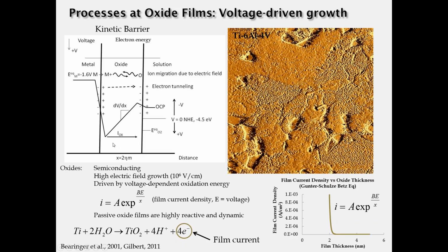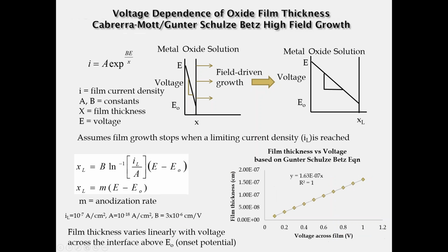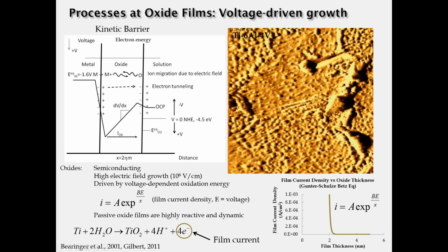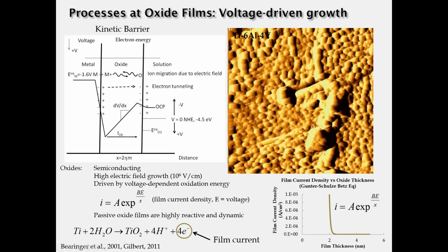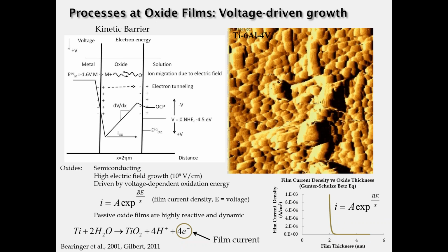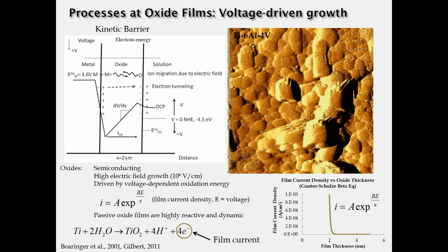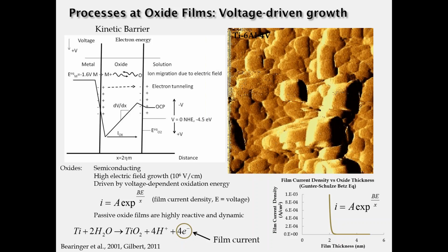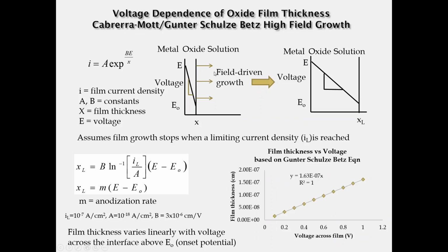And so basically, when these oxides are disrupted, they regrow to a specific thickness that depends on the nature of this equation. Let me just show you, for instance, here is an atomic force microscope animation of a titanium oxide film in solution as we start at -1 volt and increase the voltage up to +1 volt, driving the growth of that oxide film. You can see that the dome-shaped nature of the oxide coarsens and thickens over the time of that experiment. Again, this oxide film growth is driven by the electric field and also the tunneling currents to get the electrons out to the outer surface. As the film grows, you can see that the slope of that line gets less, and so the field falls away until you reach some limiting thickness where the growth essentially stops.